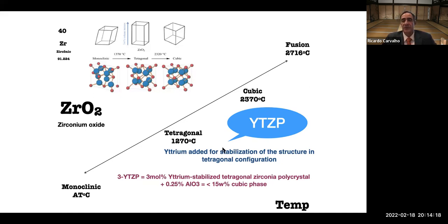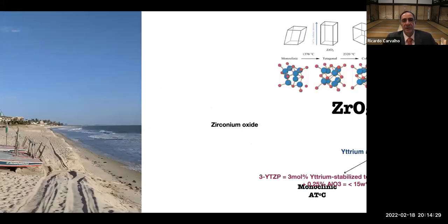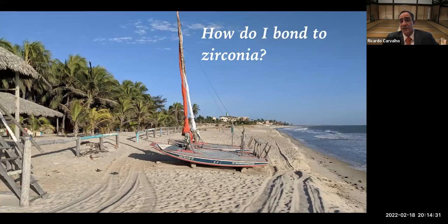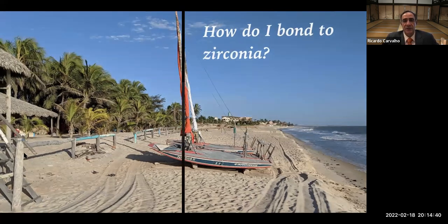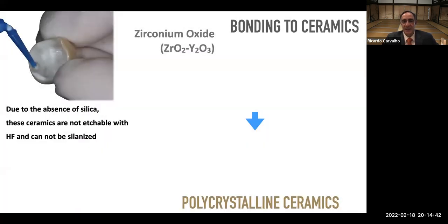And usually these materials come, in the end, with about 15% or less of the cubic phase embedded in the material during production. So that's zirconia, and that's the material that does not contain silica. How do I bond to that material then? Well, we know that bonding to zirconia is not an easy task.